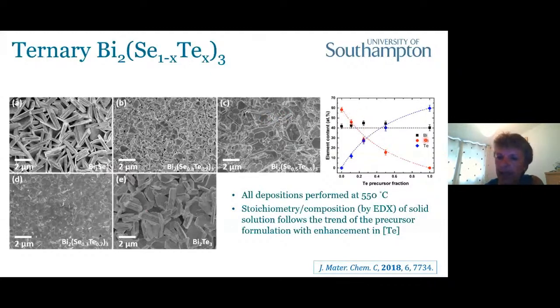If we look at the EDX analysis to get the composition, we can see that the bismuth content remains pretty close to the 40% that's expected, and we can vary the selenium and tellurium content according to the ratios that we put in. So that gives us a really excellent way of generating precursors that can give us the ternary materials.